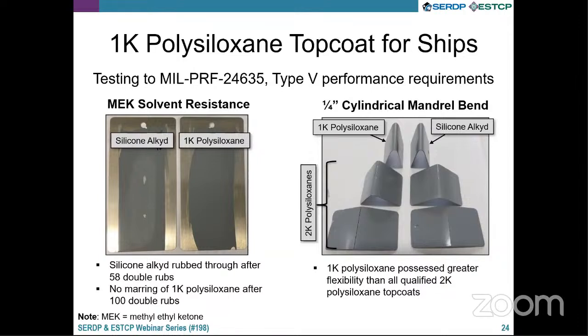Right away, doing a simple test like a MEK, methylethyl ketone solvent resistance test, you can easily see something like the silicone alkyd is rubbed through after about 58 double rubs, whereas the single component polysiloxane after 100 rubs, there's not even any marring or marks on that coating. So much higher cross-link density and solvent resistance.